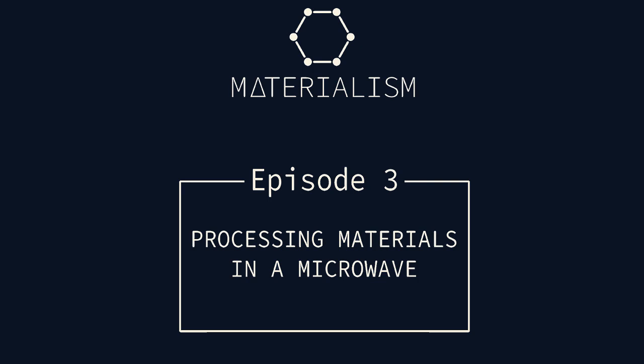And since X-ray diffraction, I mean, obviously that's great, but we have worked a lot also with sol-gel prepared compounds, and that mostly is an amorphous mixture until you reach 700 or 800 degrees C. So X-ray diffraction doesn't really get you anywhere. So we're thinking about using another technique to be able to see what is happening during the microwave processing.